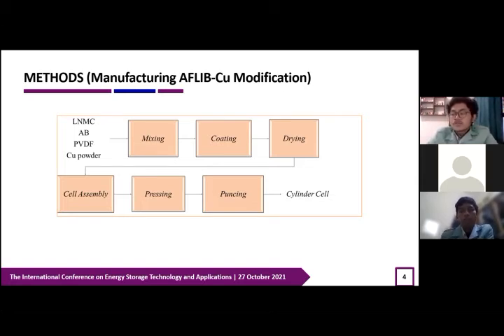The commercial LNMC cathode material that has been prepared is added with AB and PVDF until everything is homogeneously mixed, and then NMP is added until it is mixed into a cathode paste. Subsequently, the cathode paste was coated on the aluminum foil sheet using an automatic film coater. And before we coated the CU foil, we added NMP to the AB, PVDF, and CU powder. It's the same process as coating the aluminum foil.